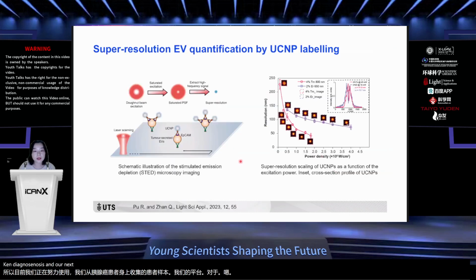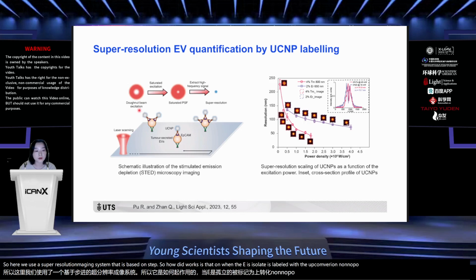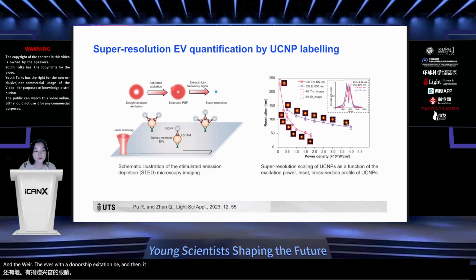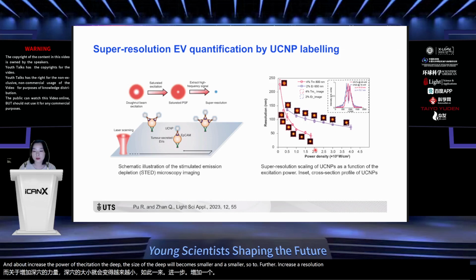In our next work, we would like to further increase the resolution of our imaging system. Here we use a super resolution imaging system that is based on STED. How it works is that when the EVs are labeled with the upconversion nanoparticle, we excite the EVs with a donut-shaped excitation beam, and then it will form a donut-shaped emission pattern. In the center, there is a dip where the nanoparticle sits. By increasing the power of the excitation, the size of the dip will become smaller and smaller, so as to further increase the resolution of our image.